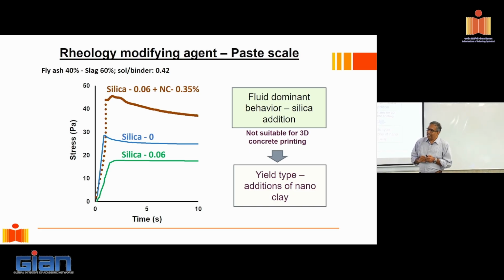Okay, what is clay? And I'm not adding clay to the extent of, say, producing LC3 cement. Small amount of clay. In fact, initially we started with nano clay and we were adding it at about 0.35%. What is the beauty of clay? Clay is a wonderfully thixotropic material. What do you expect when you deal with a clay slurry? Well, when you shear it very fast, right, the structure breaks, right? Initially, you have big clumps of clay that come together. If you shear it fast enough, these will break up into individual particles, right? Then if you let it sit, what happens?